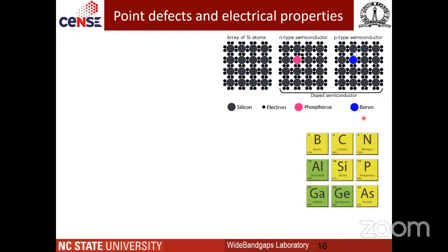So that's how you make n-type semiconductors. In p-type, what you do is, instead of group 5, you now substitute with a group 3 element, boron in this case. What boron brings along is a deficiency of an electron. So you see here that now your lattice has one deficient electron. And now this deficiency can also be loosely bound, and if you give it sufficient energy, then you can have an electron occupy this hole, and in this process you are creating a hole at the original site from where the electron originated, and that's how you can transport the hole inside the semiconductor. So that's how you make p-type semiconductors.